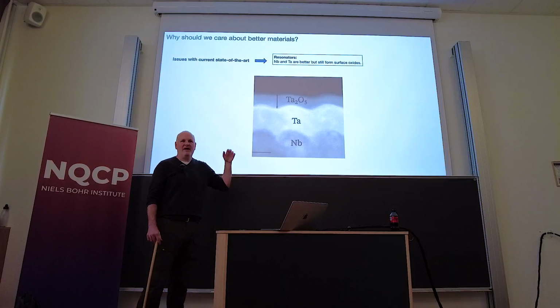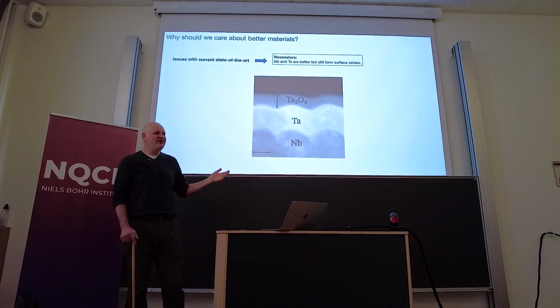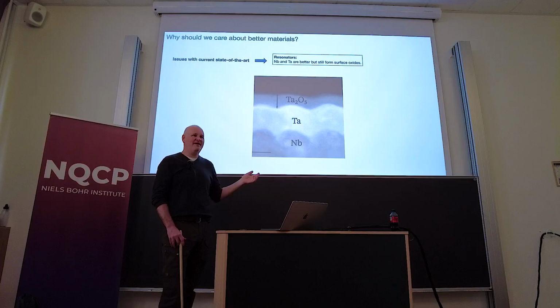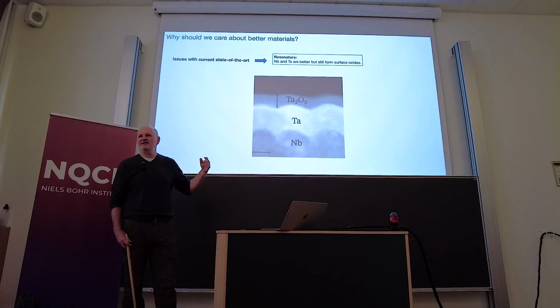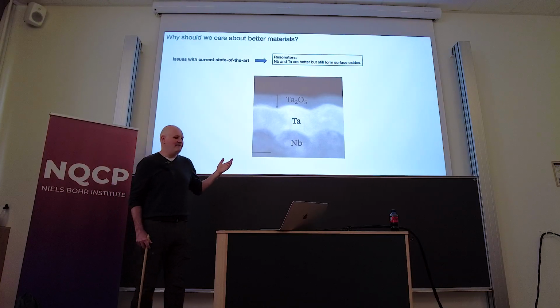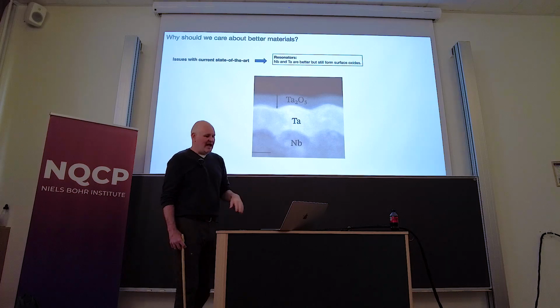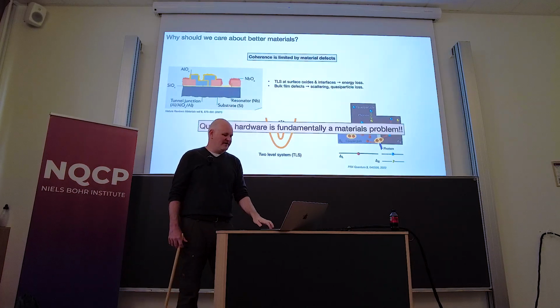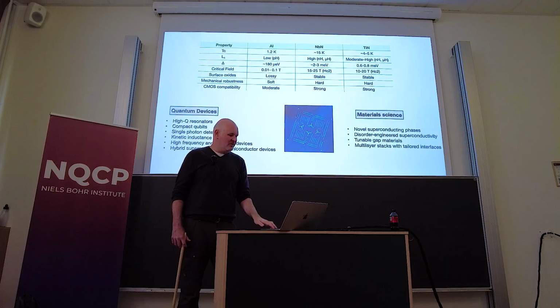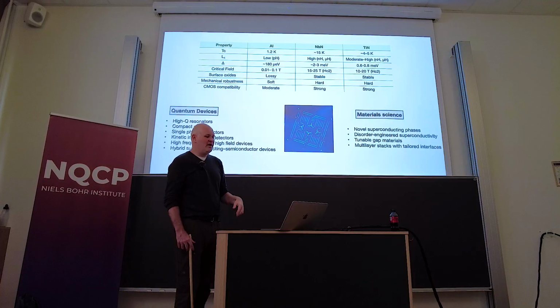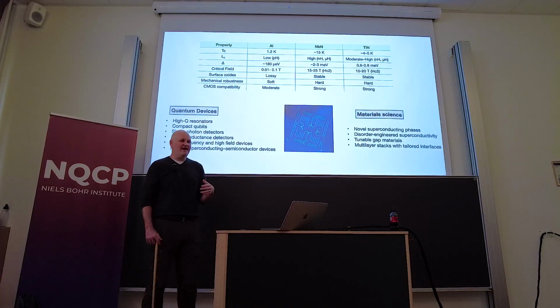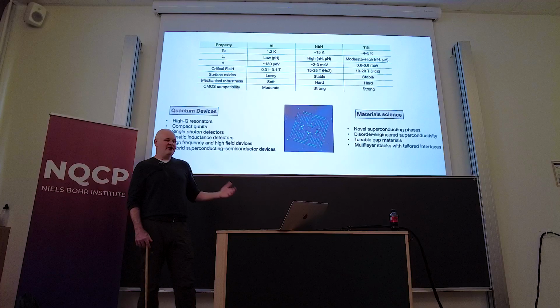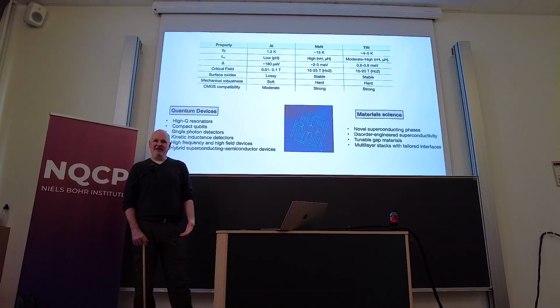So tantalum is sort of the material of choice right now. It's largely because tantalum oxide is a more stable oxide. It seems to be less lossy, but it's still not ideal. And I'm just going to skip this. And so what we wanted to do, as I alluded to before, is use our sputter chamber to develop nitride-based materials. There's a variety of reasons.